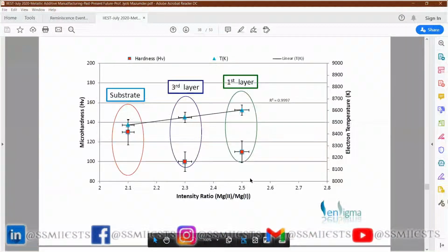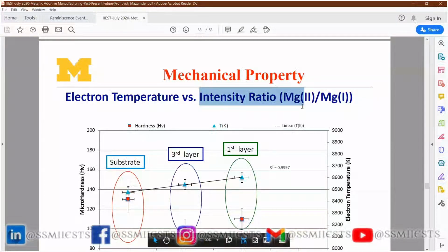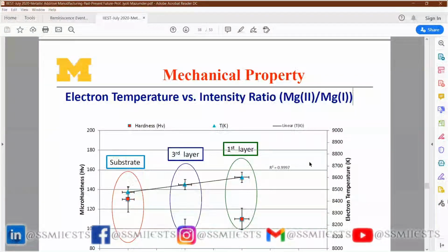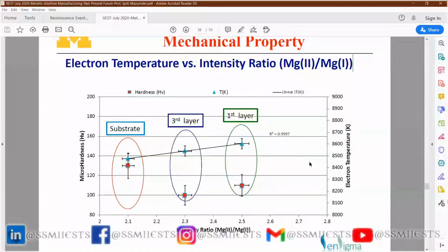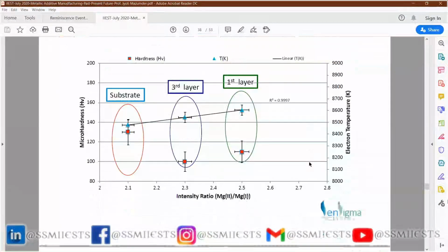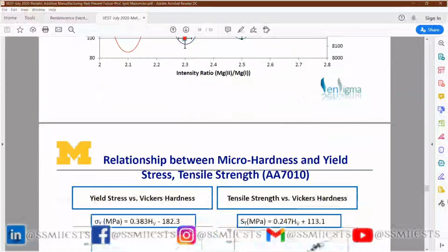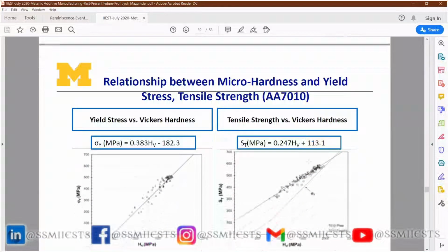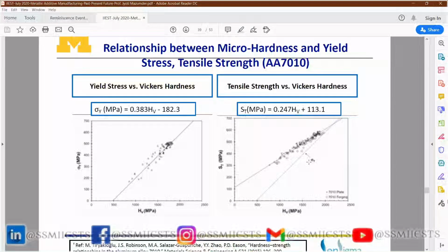So as a metallurgist, our golden rule is to find out the relationship between the processing parameter, microstructure, and mechanical property. What we revealed in the last 5 years of work shows that by looking at the plasma during the process, I can tell you the defect, I can tell you the mechanical property, and from there we can find out the yield stress versus Vickers hardness. So if I know the hardness, I can also find out the yield stress of the material. So all these are coming together, putting that into a nice ribbon and giving you the information.